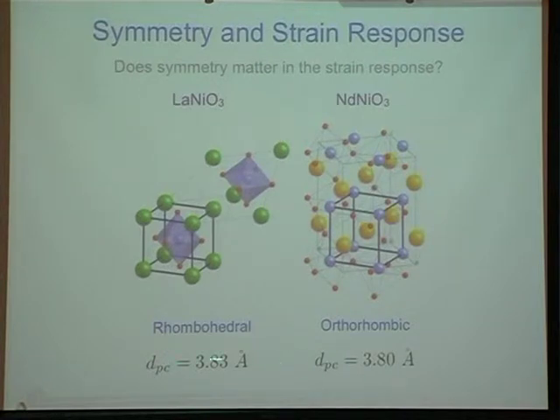So we did an example experiment where we compared lanthanum nickelate, which is rhombohedral, to neodymium nickelate, which is orthorhombic. These have, if you think of this as a pseudo-cubic structure, very similar lattice parameters, but obviously they have very different symmetries, and I'll talk a little bit more about this in a second. And so the question is, how do these respond to strain?